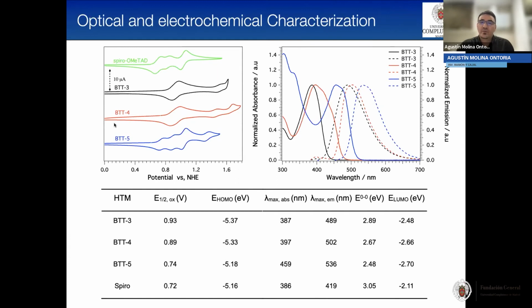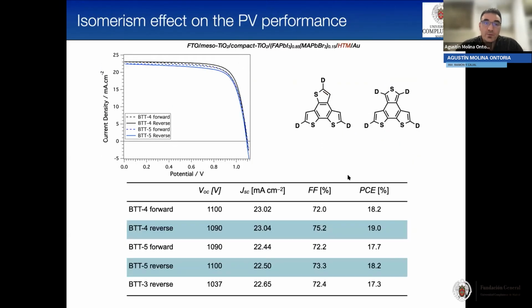Well, from the optical properties, we can see that BTT5 is significantly redshifted due to the enhanced pi electron delocalization of the central scaffold of the BTT5, and for BTT4 the absorbance is much broader than the BTT3 due to the direct conjugation between these thiophene rings that are facing in the same direction. From here, we can estimate the optical band gap, and then we can estimate the energy of the LUMO. Well, we sent these molecules to Professor Nazeeruddin in Switzerland, as I said before, and they prepared a mesoporous structure with the mixed cation, mixed anion perovskite.